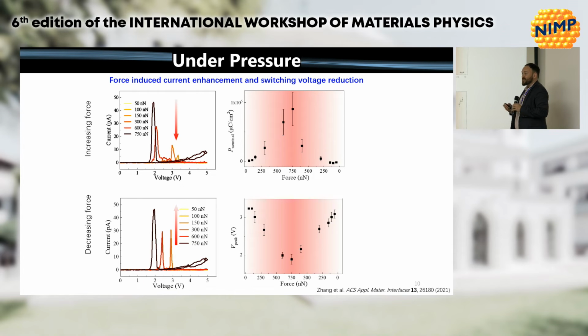We tried to estimate whether or not this was realistic. It's in the paper, kind of in the supplementary material. But we estimate that for that 50 nanometer film, where we have a few nanometers of dead layer, of interface layer, this would correspond to a change in that film thickness of at least a quarter of a nanometer. And that would give rise to on the order of a volt, a little bit less than a volt.